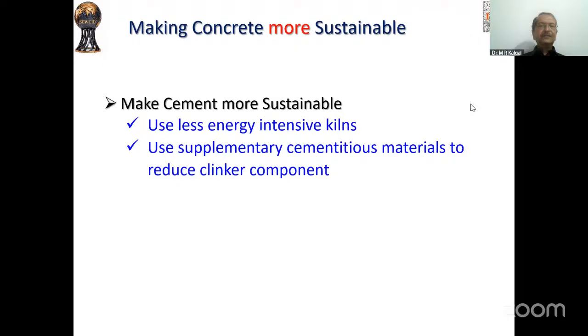Please remember that the statement that 1 ton of cement produces 1 ton of carbon dioxide is with OPC and the clinker in mind. If it is 100% or 95% clinker, then 1 ton of clinker production resulting in 1 ton of carbon dioxide was true. But with all the improvements at the factory and resource extraction, people have now brought it down to about 0.7 tons per ton of clinker. Now use supplementary cementitious materials like fly ash or GGBS or any other materials. Obviously, you'll be reducing the clinker content. So the reduction in clinker factor will make it more sustainable.